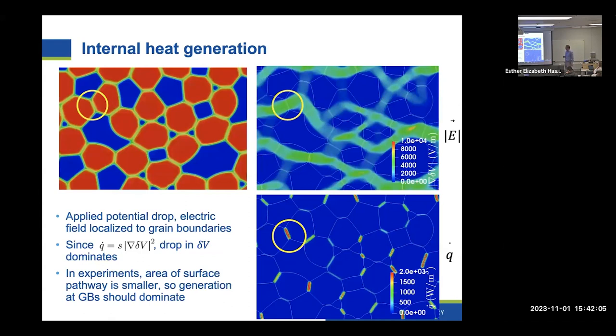So to try to understand that, I also plotted out the magnitude of the electric field here. So this is the magnitude of that applied field. And if you look at that, those potential drops are actually predominantly localized at the grain boundaries. And if you look at the equation for Joule heating, it's linearly proportional to the conductivity, but it's proportional to the electric field squared. So even though the conductivity is lower at the grain boundaries, the electric potential drop is higher, and so the drop in the potential actually is what dominates.